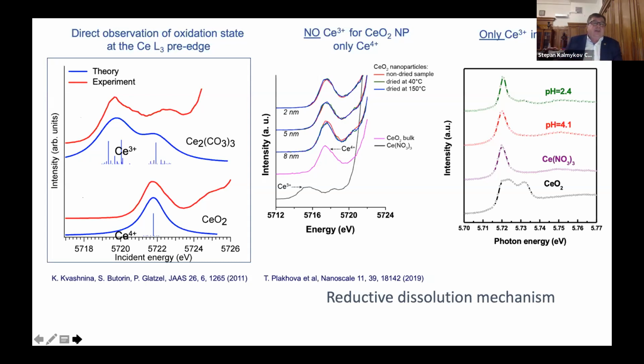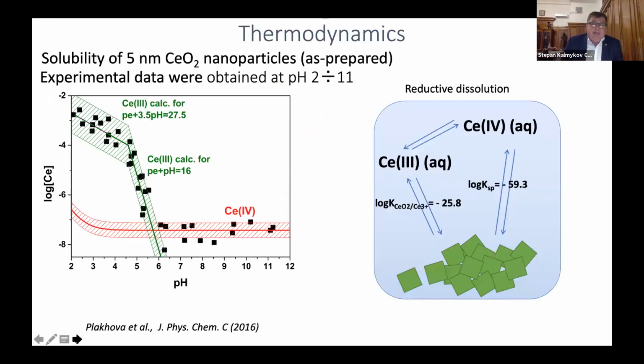This is different if we take the solution. When we analyze the solution, depending on the pH, we have only Ce(III) in the solution. So it is very probable that we have a reductive dissolution mechanism of these cerium dioxide nanoparticles. And for solubility, we made solubility measurements with a radioactive tracer of cerium-141. And depending on the pH, for the first time, we made very precise measurements of the equilibrium constants of this reaction. So at low pH, we have the reductive dissolution. At the higher pH region, we have the oxidative dissolution, where we have Ce(III) in the solid phase and Ce(IV) in the solution. At the lower pH, we have Ce(IV) in the solid state and only Ce(III) in the solution.